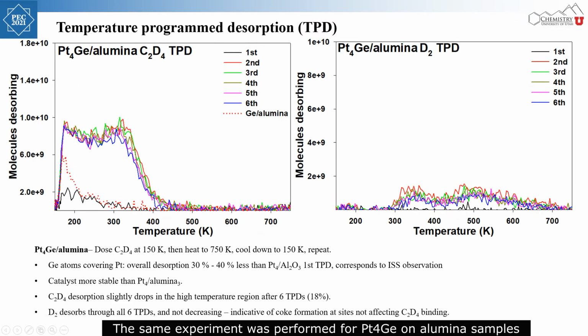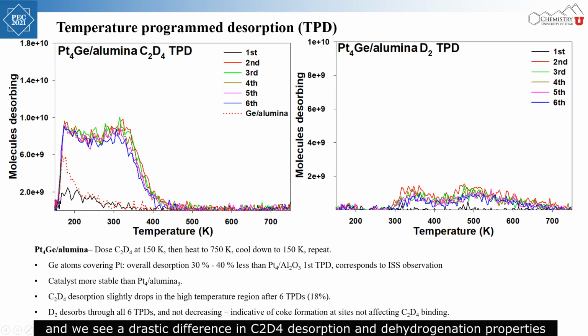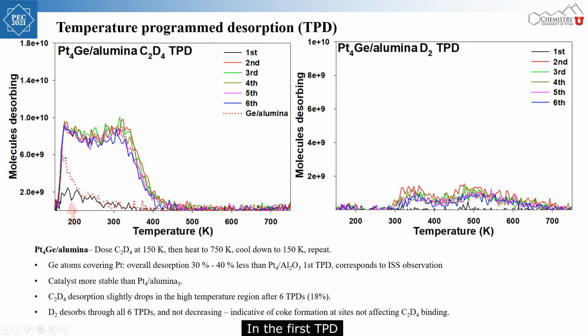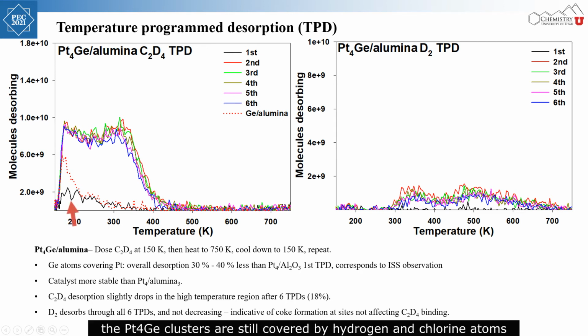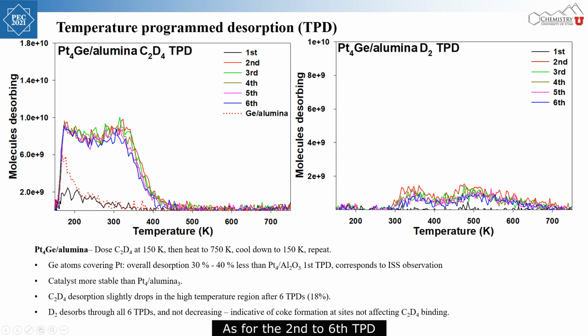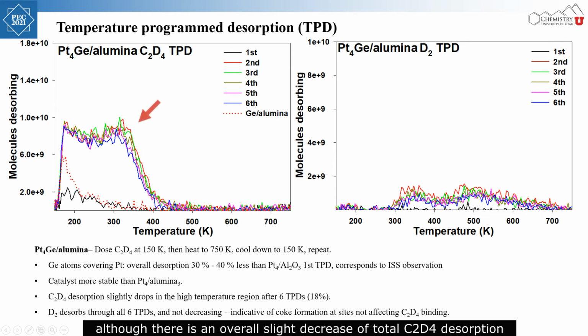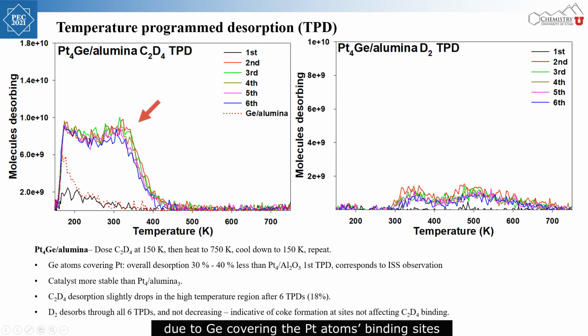The same experiment was performed for platinum-4 germanium on alumina samples, and we see a drastic difference in C2D4 desorption and dehydrogenation properties. In the first TPD, the platinum-4 germanium clusters are still covered by hydrogen and chlorine atoms, so the C2D4 desorption and dehydrogenation were negligible. As for the second to sixth TPD, although there is an overall slight decrease of total C2D4 desorption due to germanium covering the platinum atoms' binding sites,